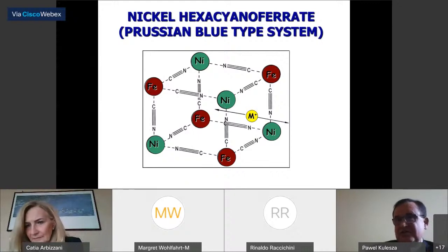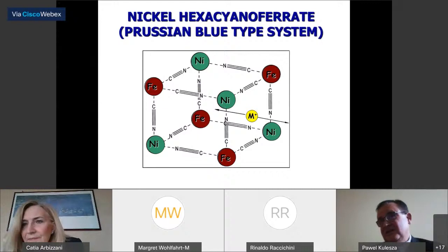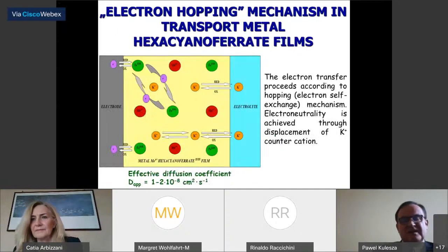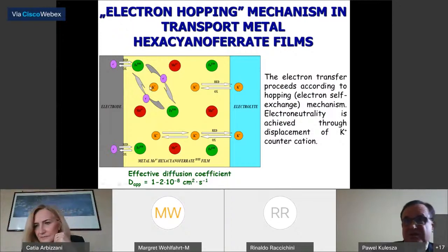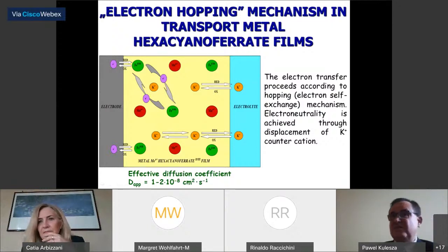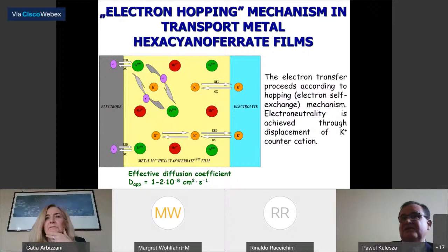And the counter-ion motion is quite important. Nickel is more layered type system, I would say, resembling more clays than zeolites, and is extremely fast in charge propagation. So electron transport is accompanied by motion of counter-ions. Diffusion coefficients are moderate, so we were aware that we will not break through in certain applications, but for sure, as was demonstrated in recent years, it is definitely good for charge storage.